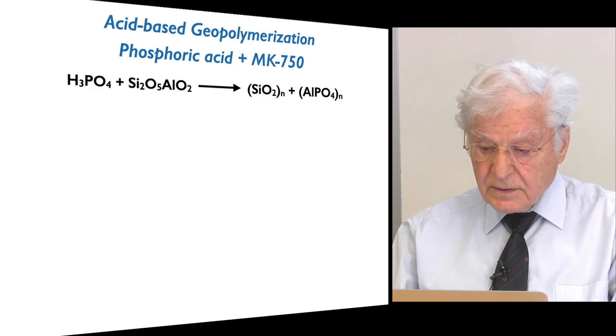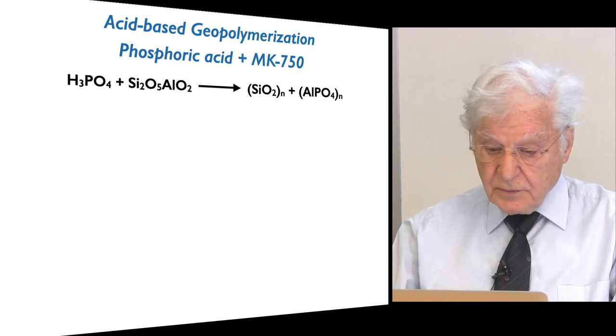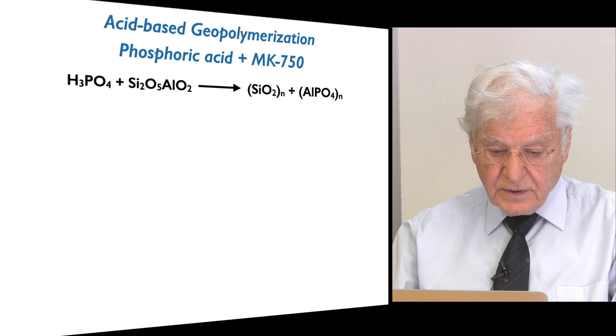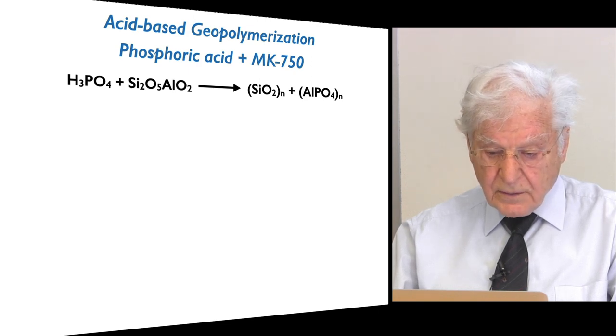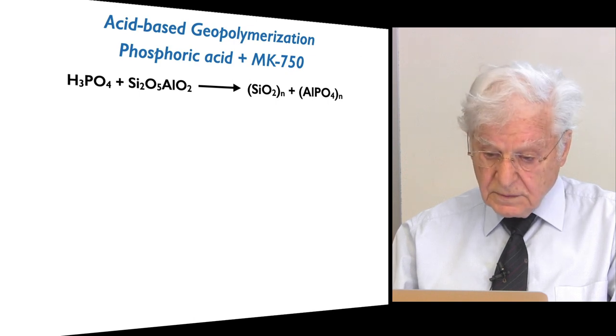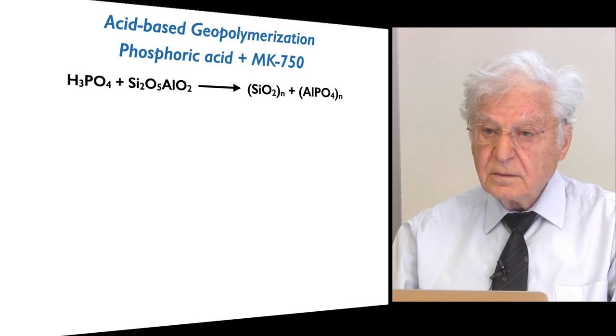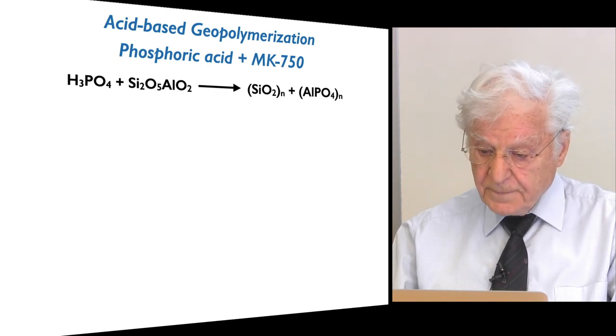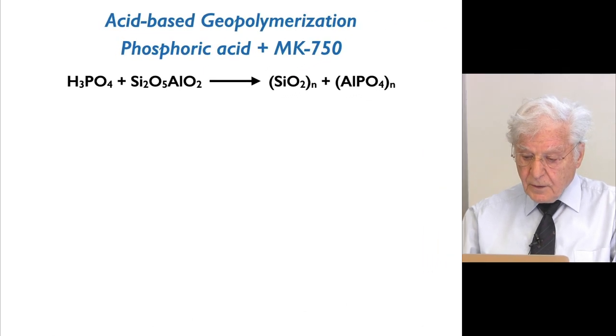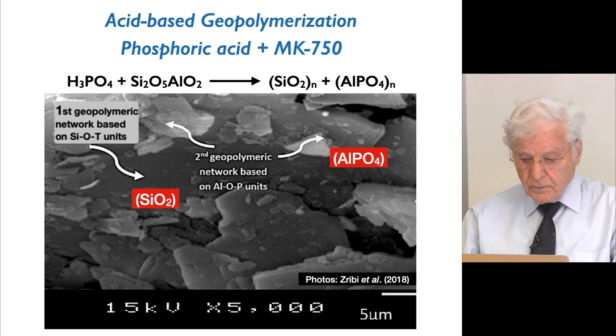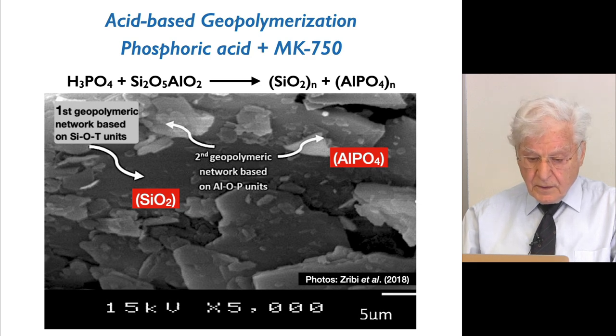Phosphoric acid reacts with metakaolin according to the chemical reaction: phosphoric acid, H3PO4, and metakaolin, which yields SiO2 and aluminum phosphate, which is a macromolecule, which I'll call a geopolymer. One gets a mixture comprising two geopolymeric networks that we see under the electron microscopy. First geopolymeric network based on SiO units, in dark, SiO2, and second geopolymeric network based on aluminum phosphate units.